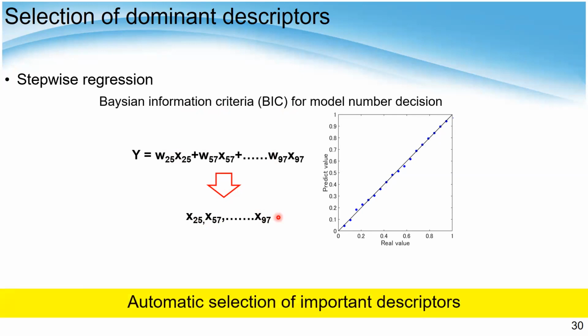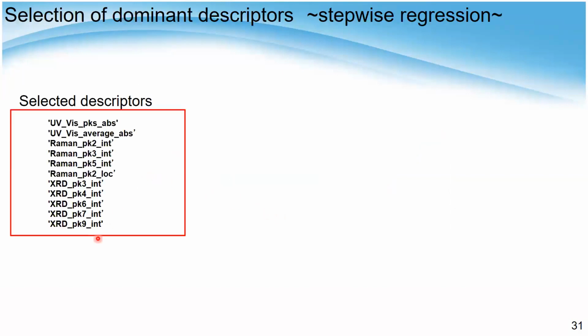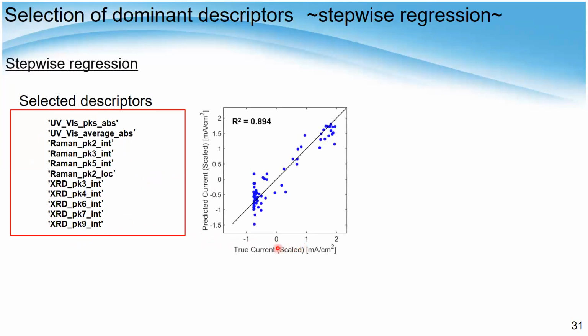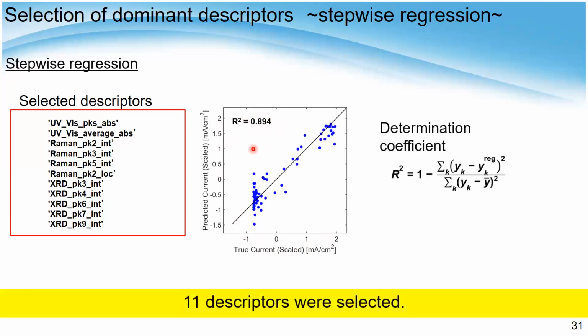So in essence, we can automatically select most of the important descriptors. And here's a selection of the important descriptors. And then here's a response plot for the true current and predicted current. And this R2 value is the evaluation criteria. And simply here I say the determination coefficient R2, the closer to 1, means the good prediction. And during this process it was about 0.9, which is quite high.